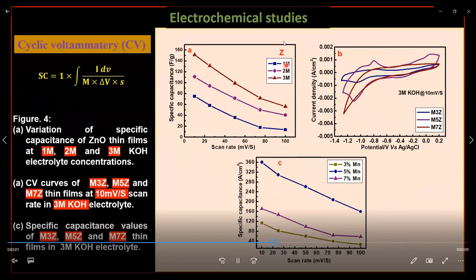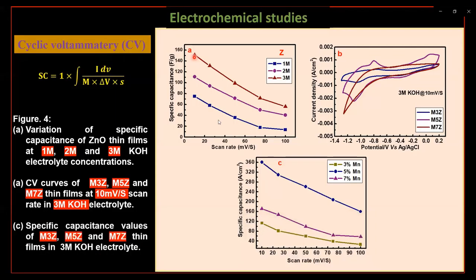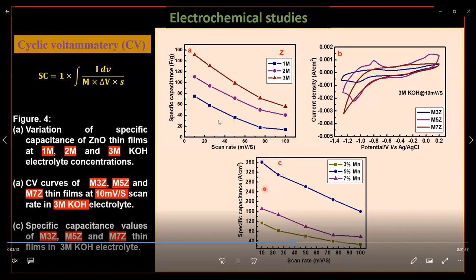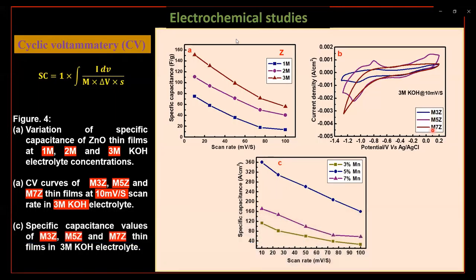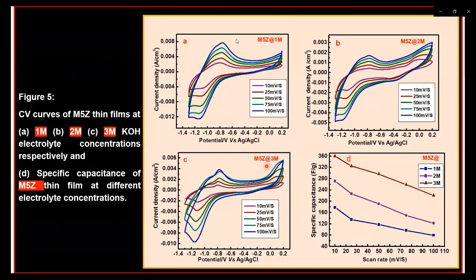And as concentration increased from 1 molar to 3 molar, at 3 molar concentration, the ZnO shows the highest specific capacitance, 151 farad per gram. These are the CV curves for 3%, 5%, and 7% Mn content in 3 molar KOH, and this 5% Mn doped in ZnO exhibits higher specific capacitance, which is 361 farad per gram.